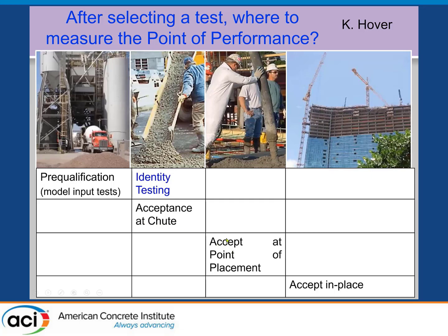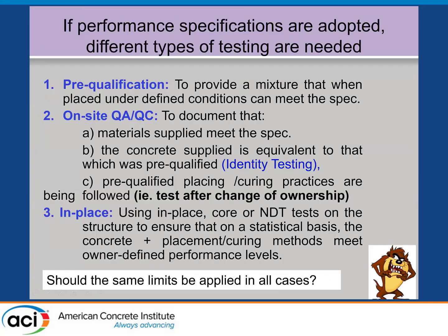Some people like to do it at point of placement because pumping or other transport of the concrete may affect the results. But the owner doesn't care about any of that because the owner wants a structure that meets the requirements. So they would prefer in-place testing, and some highway departments have gone that route. And so if we adopt performance testing, we need a pre-qualified mix that can meet the spec, or when it gets on site, that it's the same concrete that was delivered, as I mentioned, and it meets the spec. In-place testing, we've got to take cores or do NDT tests that on a statistical basis show that not only the concrete, but the placing and curing methods also meet the performance levels that have been predefined.